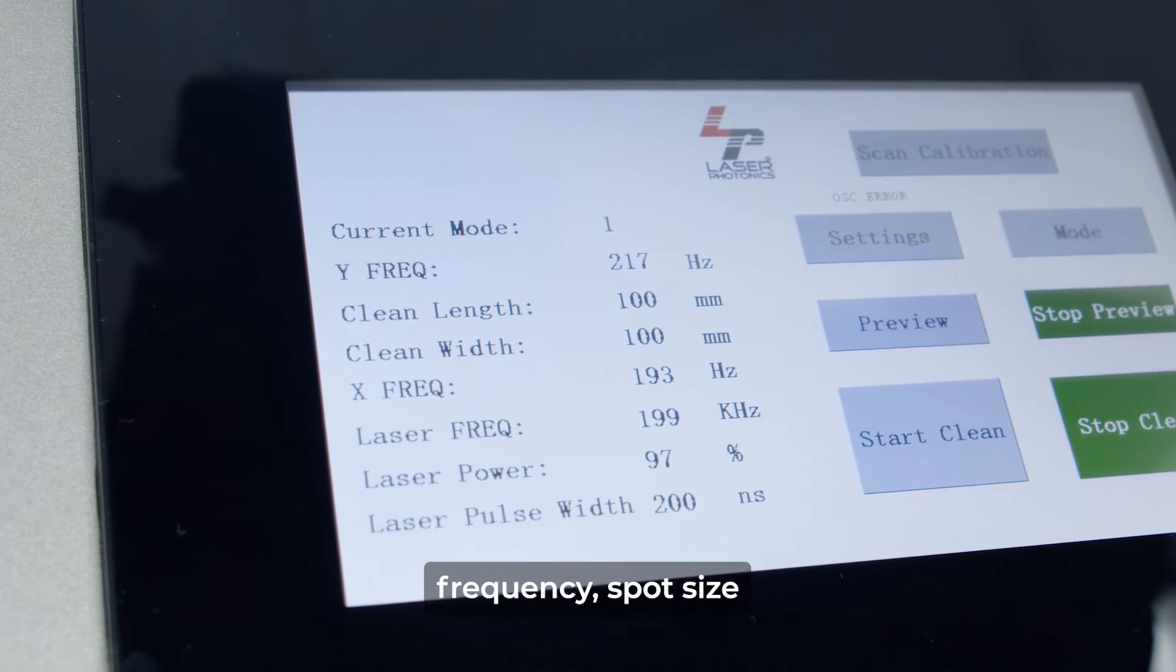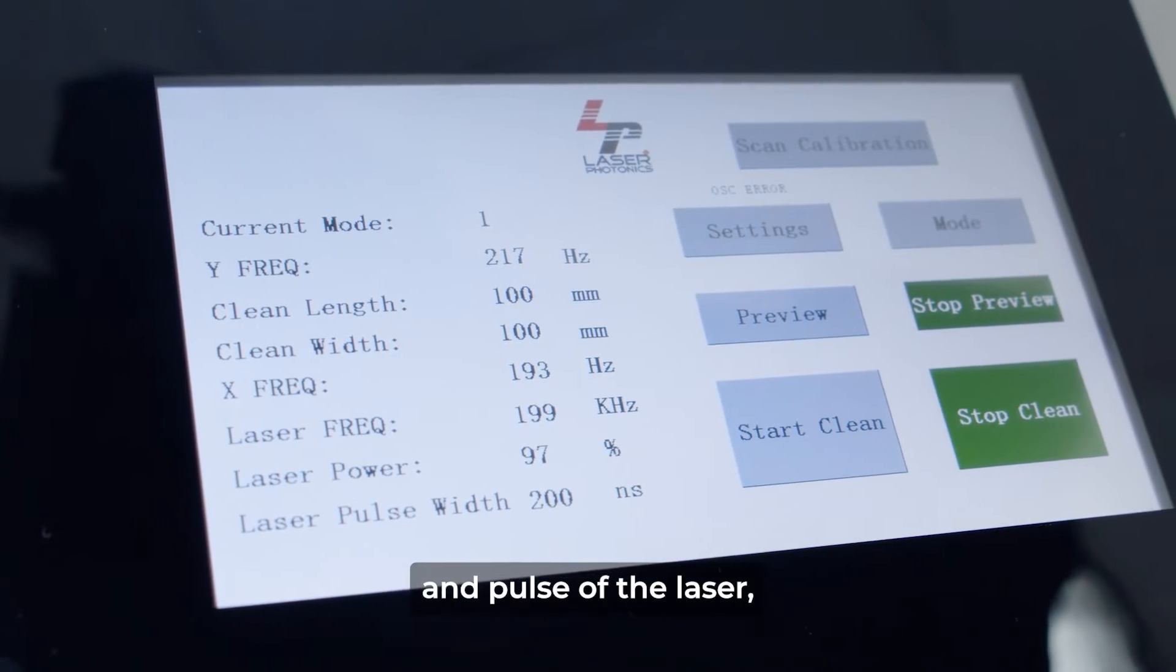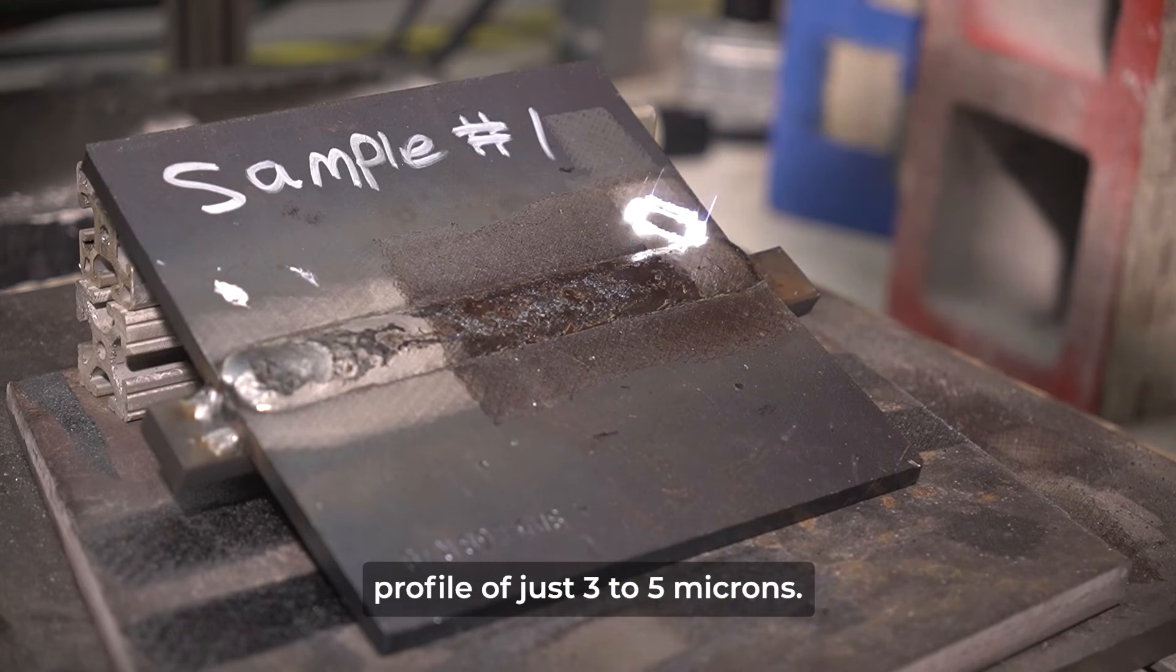By adjusting the power, frequency, spot size, and pulse of the laser, you can achieve a surface profile of just 3 to 5 microns.